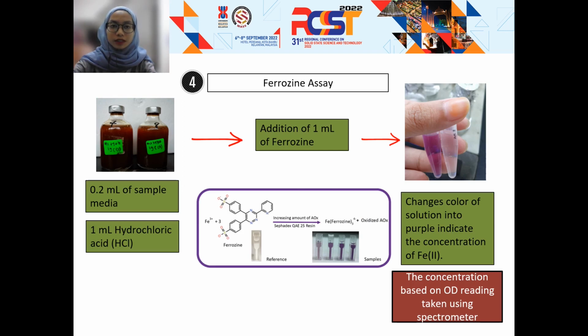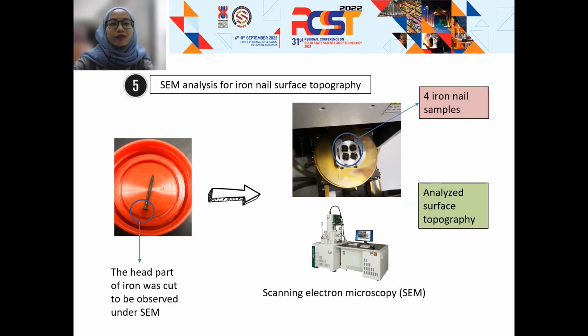Throughout the experiment, the iron 2 as the product of iron 3 reduction was monitored via ferrozine assay. The purple color indicates a positive result, while a colorless solution indicates a negative result. The positive results were measured at 562 nanometer absorbance via spectrophotometer. Finally, the corroded iron nail was taken out and cut prior to surface topography analysis via scanning electron microscopy.